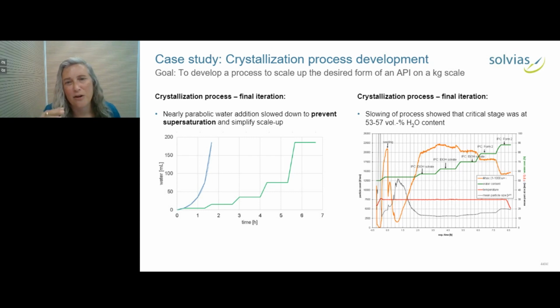And if you look here on this curve, you can see the green steps are the anti-solvent dosage. We took in-process controls, and we could see the first 3 were ethanol solvate, but then we had a smooth transition to form 2, where we actually see that the mean particle size increased. And so, avoiding a gel, we were able to produce form 2 in solution.